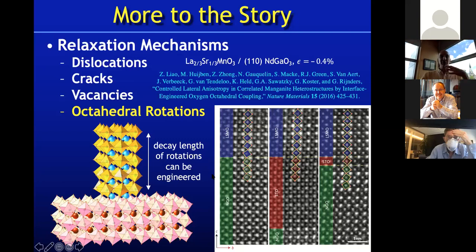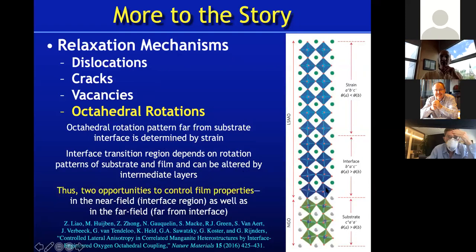Okay, so now with this added richness of octahedral rotations, you can think of going from the substrate to deep into the film where there's a steady state, well, not so deep that you've started to have dislocations or cracking, but deep enough that you get to the steady state strained value of the octahedral rotations in the film. And there's this transition region where you go from the octahedral rotation pattern of the substrate to that of the film. And this, of course, brings out not only the richness of the system, but also the opportunity that, what I'm calling strain engineering in the case of these perovskites, is also the opportunity to do octahedral rotation engineering. And it may be that you're going to get the properties that you want from this interface region, from what I'm calling the near field region, the region that's close to the interface,